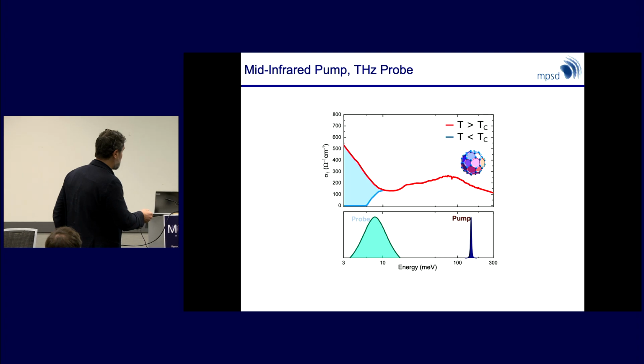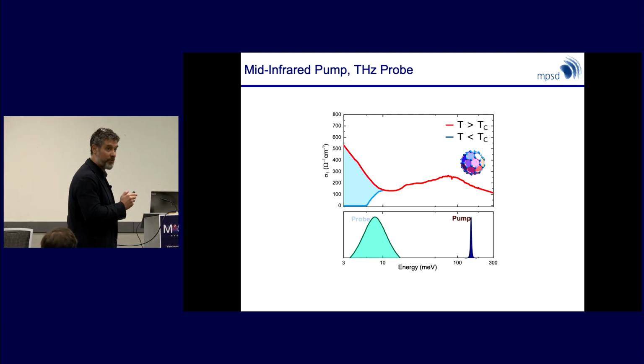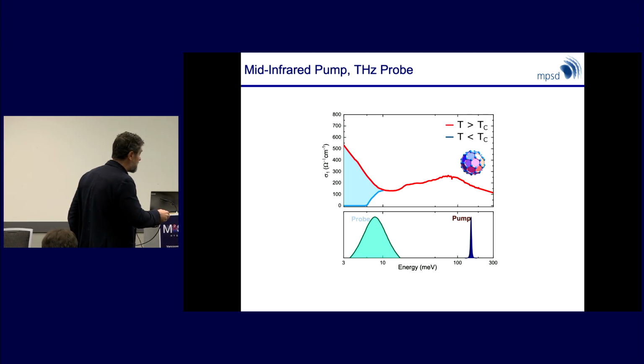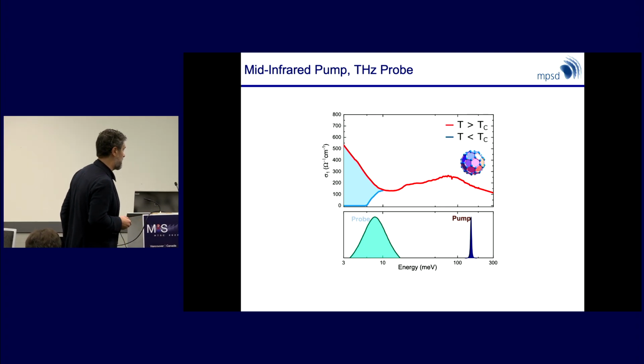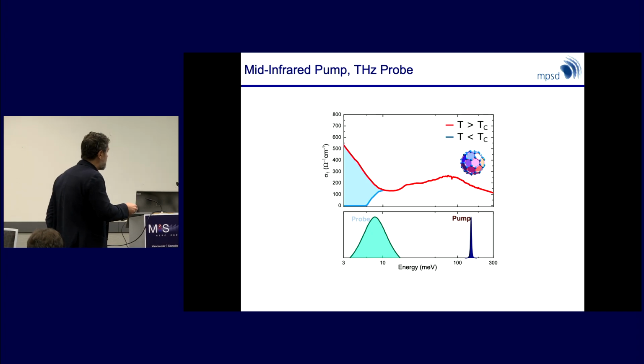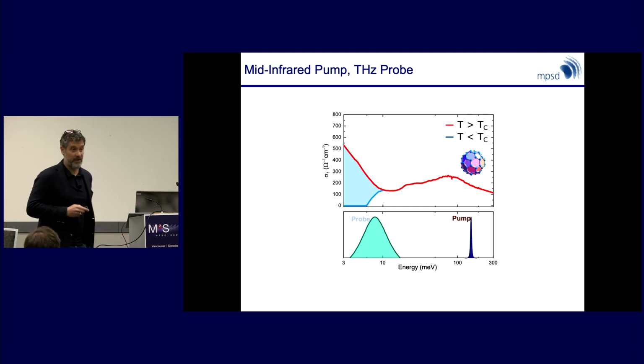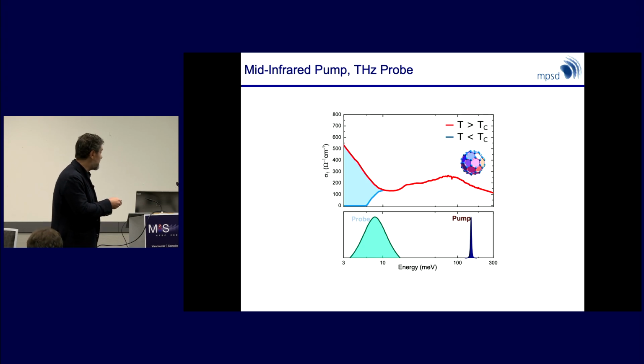And so this is the way we do the experiment. It's a pump probe experiment. We pump in the first generation of experiments. Matteo pumped around here at about 7 microns. And then we would use a probe pulse that would interrogate the material here in the region of the gap, so where the difference between the metallic state and the superconducting state are particularly stark.